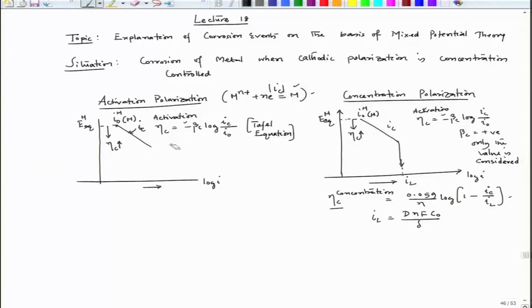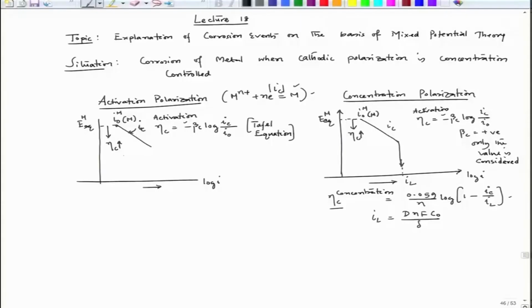Now, there could be a situation that the cathodic reaction is in the activation control zone, and there could be a situation that the cathodic reaction is in the concentration control zone. So, in one case the cathodic polarization within this zone is always in the activation control zone, and in another case the cathodic polarization can reach this, which is the concentration controlled zone.